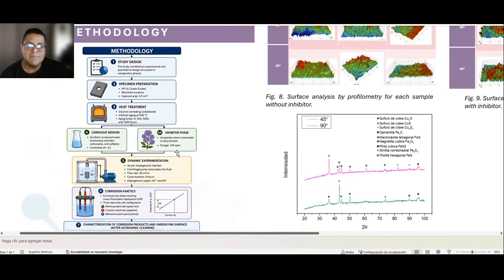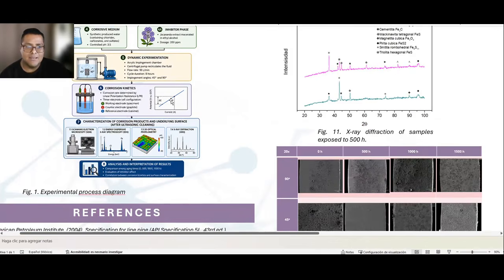To simulate a dynamic environment, we used a two-outlet impingement chamber. The centrifugal pump circulated the fluid at 18 liters per minute for 8-hour cycles. We designed two specific angles, 45 degrees and 90 degrees. We measured the corrosion kinetics using linear polarization resistance, called LPR, and Tafel curves in a three-electrode cell. After that, we used ultrasonic cleaning and characterized the surface and the corrosion products using SEM, EDS, 3D optical profilometry, and X-ray diffraction.